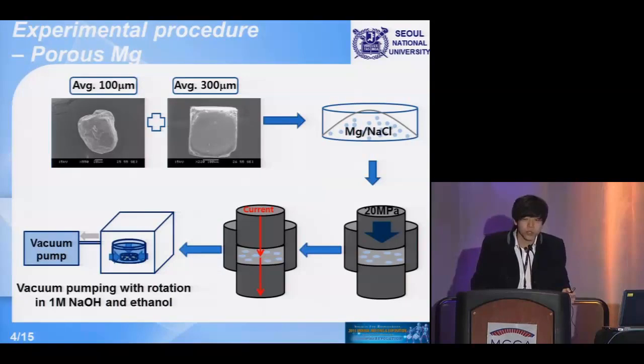And to make the porous structure, we tried to dissolve the sodium chloride, so we put the specimen inside the sodium hydroxide solution, because magnesium itself has a limitation of corrosion in a solution which has pH higher than 12. And to dissolve sodium chloride much faster and completely, we use vacuum pumping to put the solution inside the pores more easily.